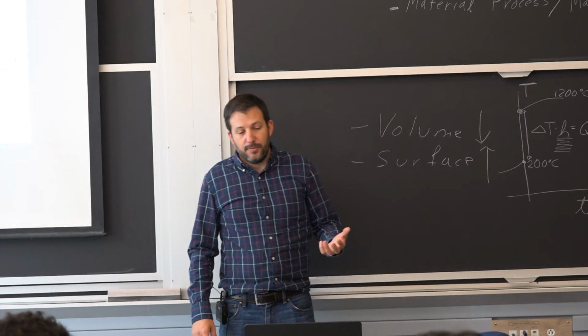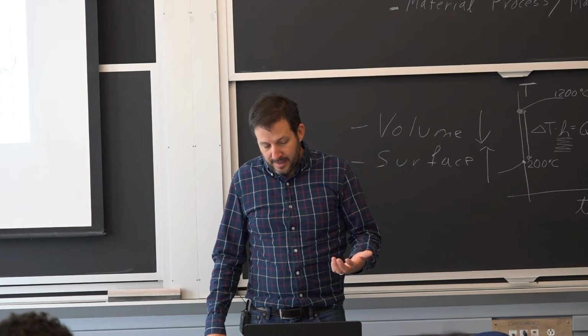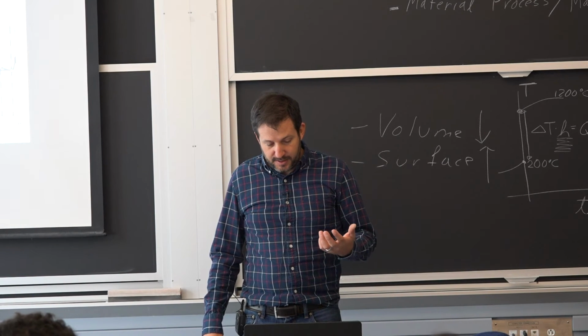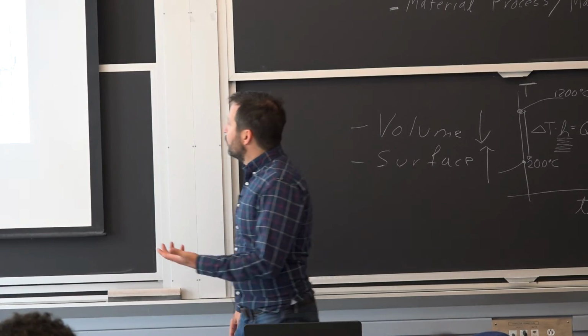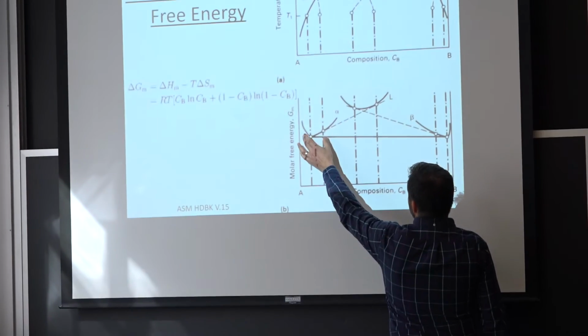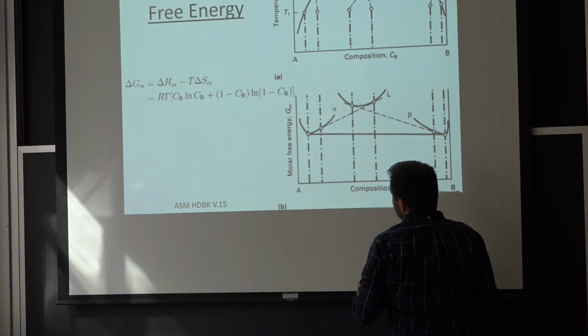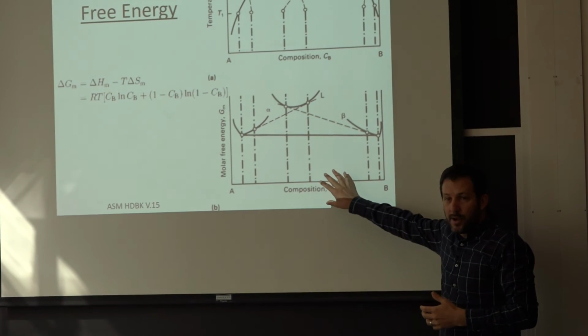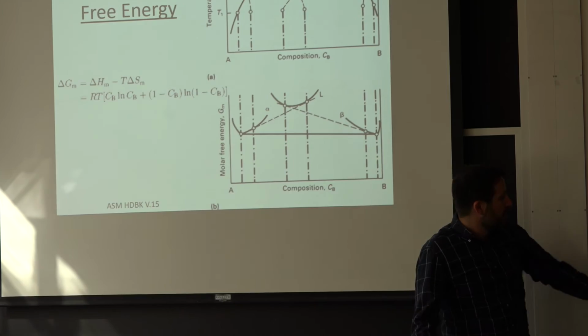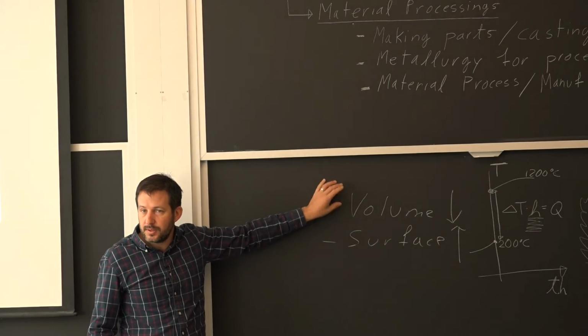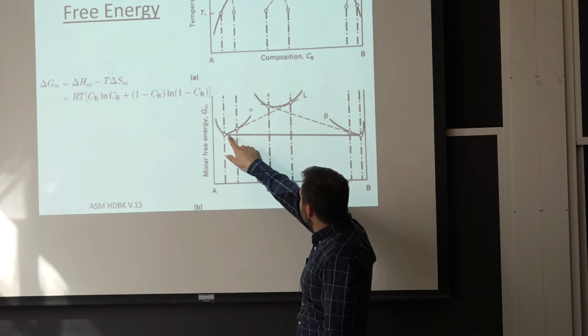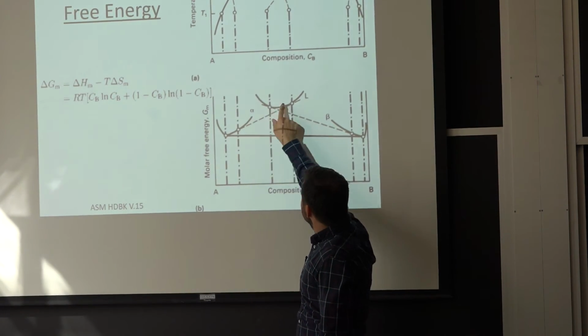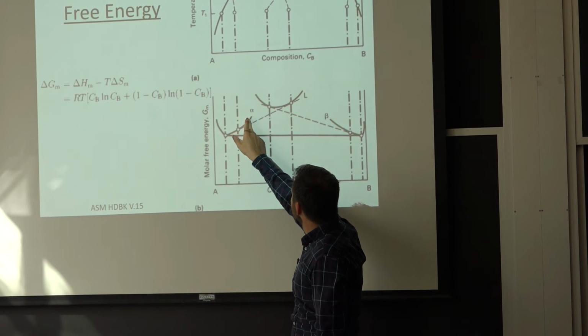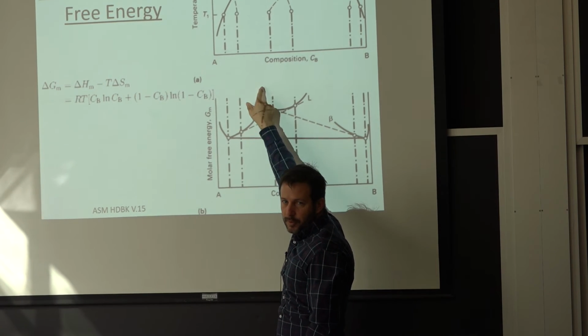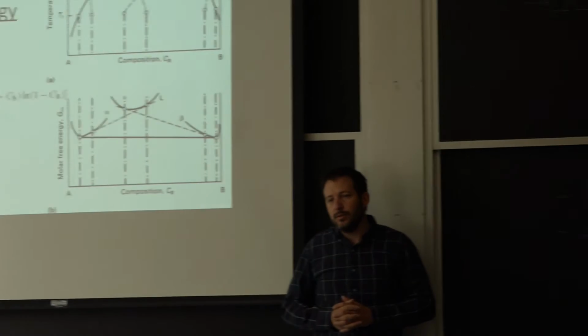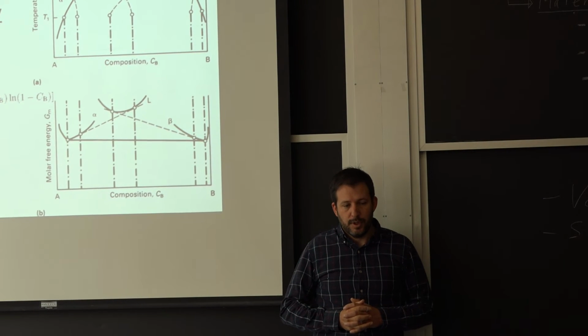So there's just a lot of thermodynamics used in metallurgy, but the basic concept is this free energy and trying to minimize it. And what we've talked about last time is, if I have a certain energy for a certain phase, another phase, this without the interface. So this analysis here has no consideration about our surface energy. This is just for the volume. It's how we determine this one. It tells me, well, I would rather have a certain fraction of this phase and a certain fraction of this phase, as opposed to having just one phase that has a higher average energy here for each of the two phases. That's how you minimize your volume total free energy.